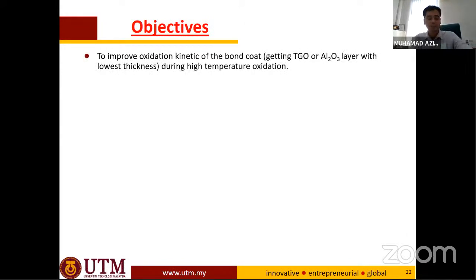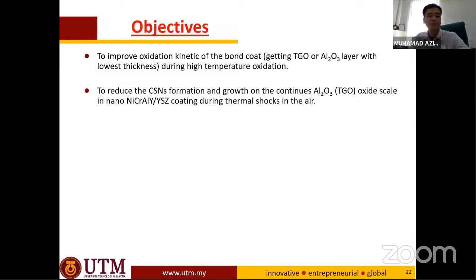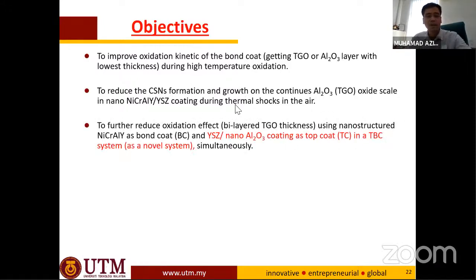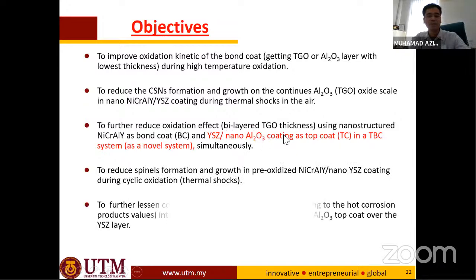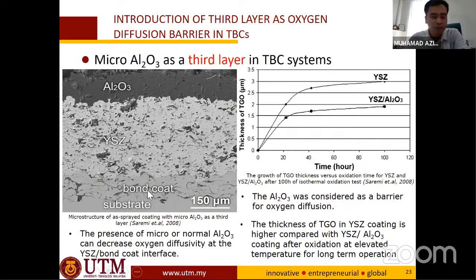The objective of the research is basically to improve the oxidation kinetics in your layer to reduce the CSN formation. As I mentioned, CSN, chromia, spinel, nickel oxide, is detrimental, so we need to reduce this. How to do that? We have nano alumina coatings on top of this system. What we do is, we have a bond coat here. This is the substrate, this is the bond coat, and then this is the ceramic coating.